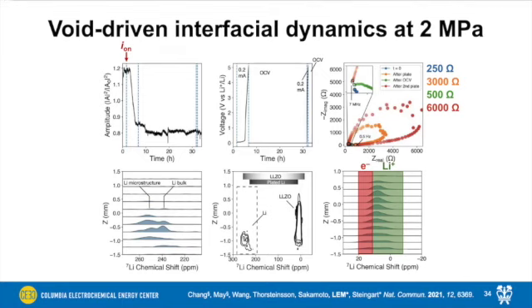So basically what we think is happening here is that these large changes, or these high impedance values, are correlated with the fact that we're forming these electron conductors at our interface at low stack pressure. So we wanted to figure out a way: could we prevent the formation of these electron conductors? Were we able to lower these impedance values simply by increasing our stack pressure?